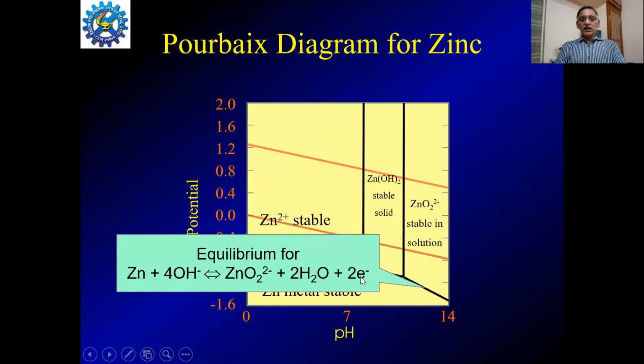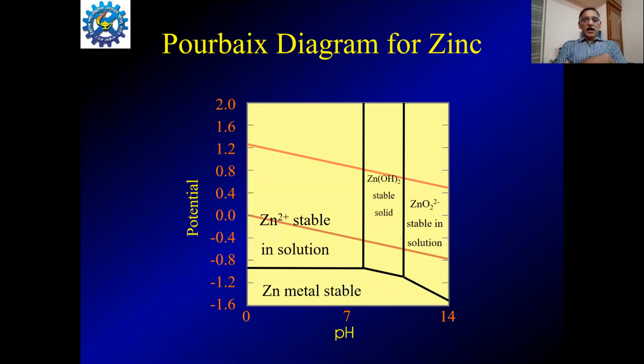The final line is zinc with a very high concentration of hydroxyl ions, which may get transformed into zinc O2 2 minus plus water plus electrons. This line gives the boundary between zinc metal and zinc O2 2 minus. This is an equilibrium between these two species. Here we have seen the species under various potential and pH conditions. For example, below this line, under various pH conditions and potential regions, zinc metal is stable. In this very big area with a boundary of this line and this line, zinc 2 plus ion is stable under various potentials and pHs. On going to higher pH, under these various potentials, zinc hydroxide is stable for a short area, and then it transforms to zinc O2 2 minus.